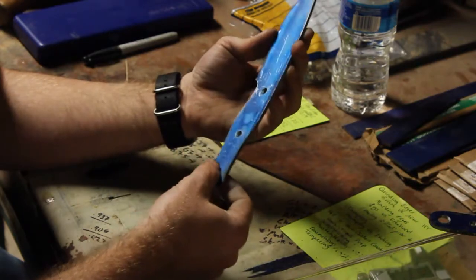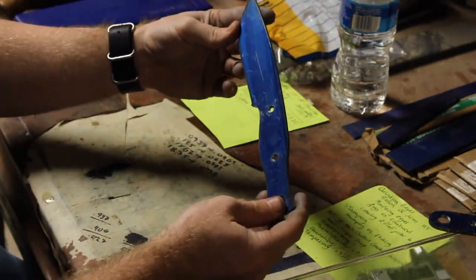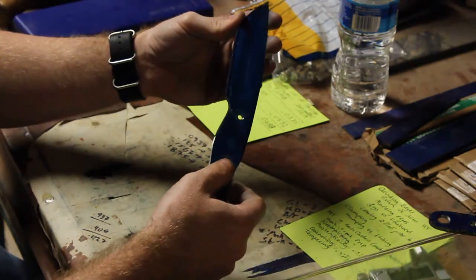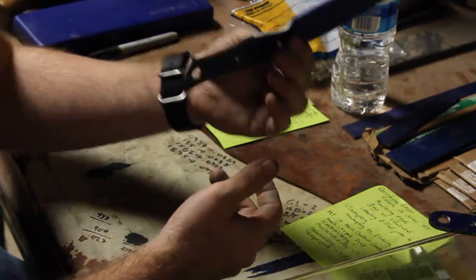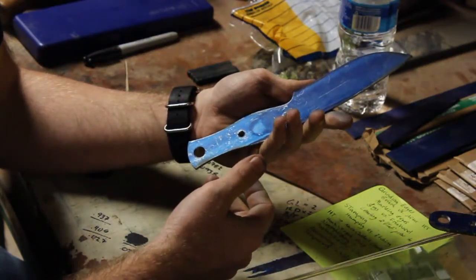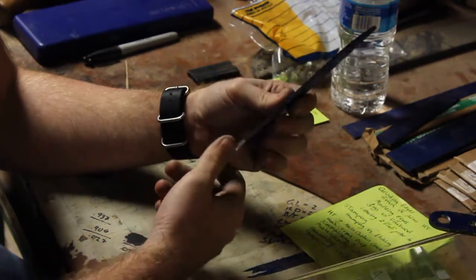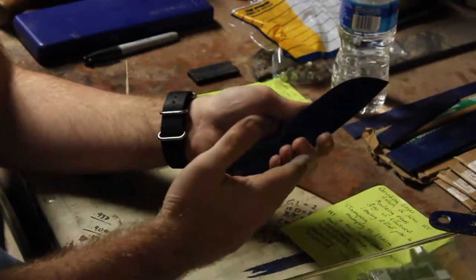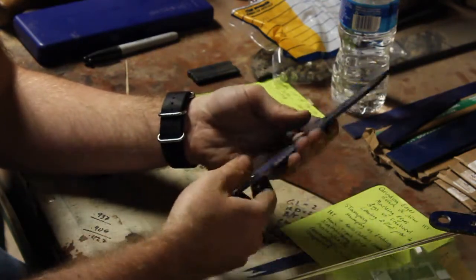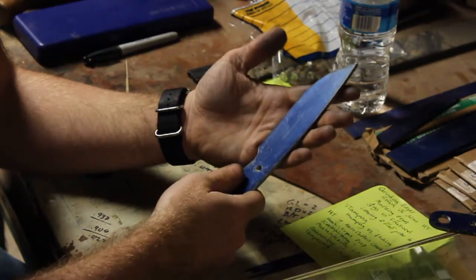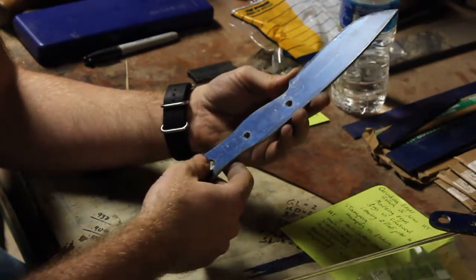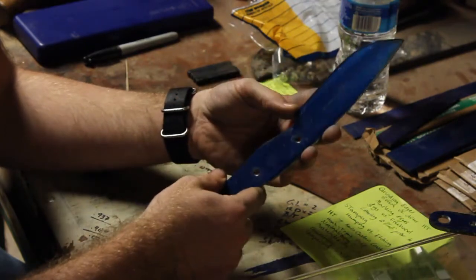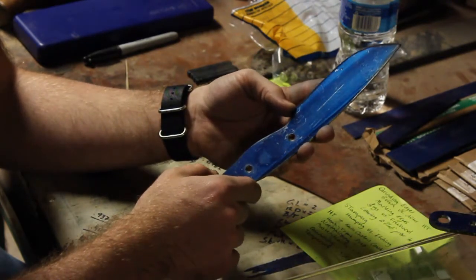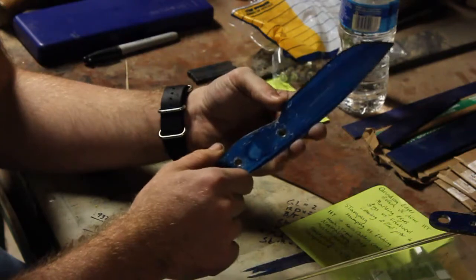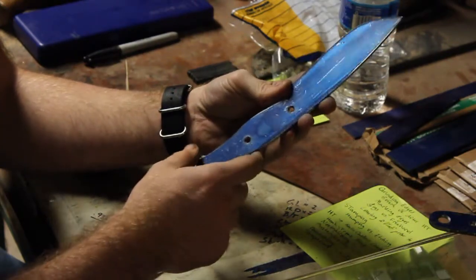Next step is austenitizing. Austenitizing occurs before you quench. It's the step where you bring the blade up to above critical temp and you let it soak. Different steels require different temperatures and soak times. I soak for 30 minutes. It's important to know the soak time for your steel. You're not going to get the most out of your steel if you do not soak it properly.